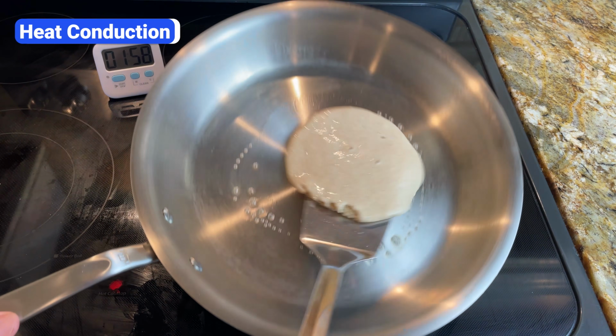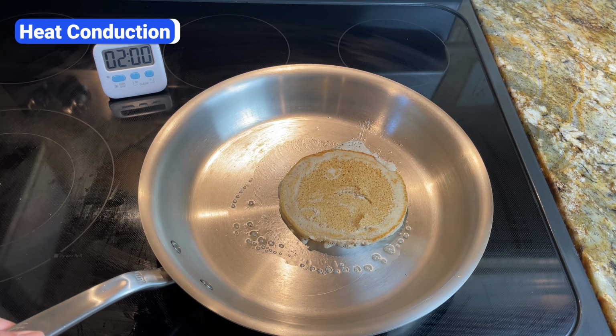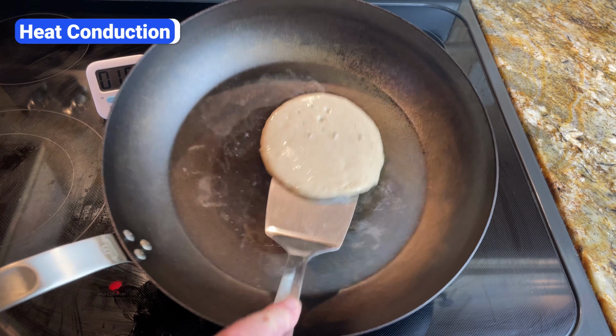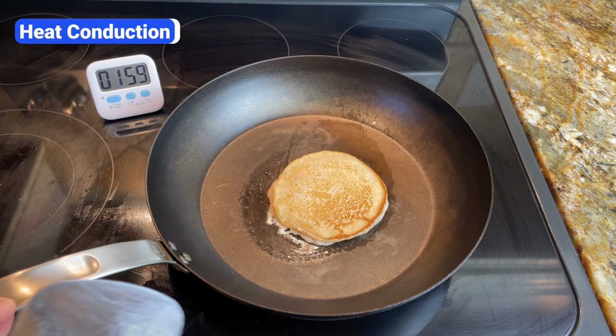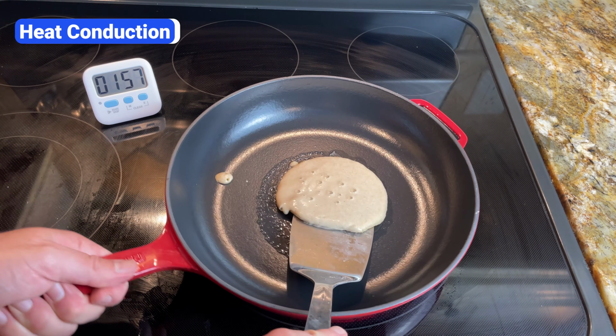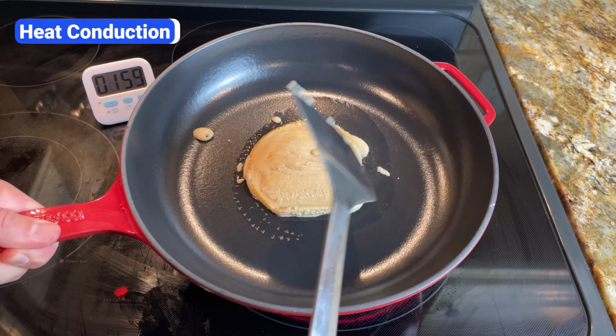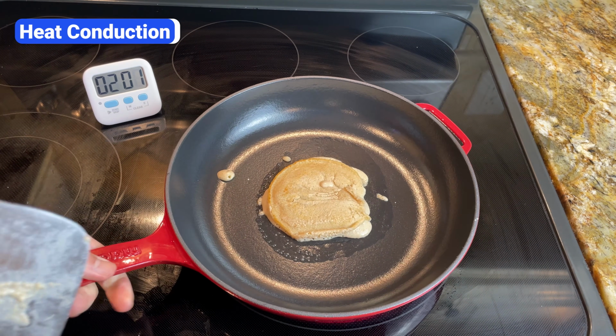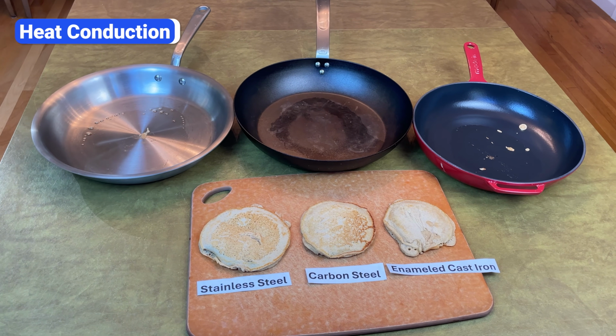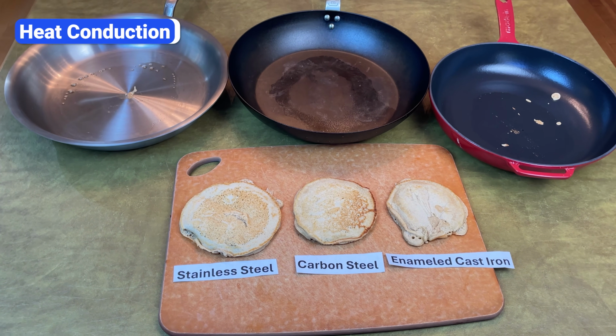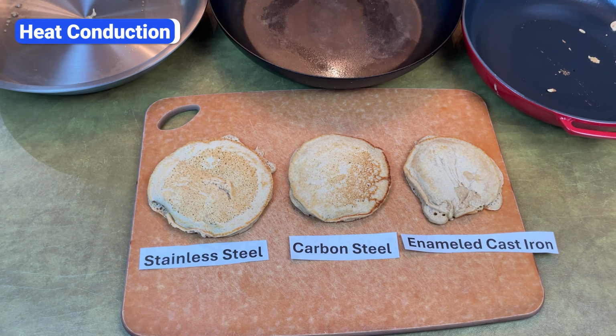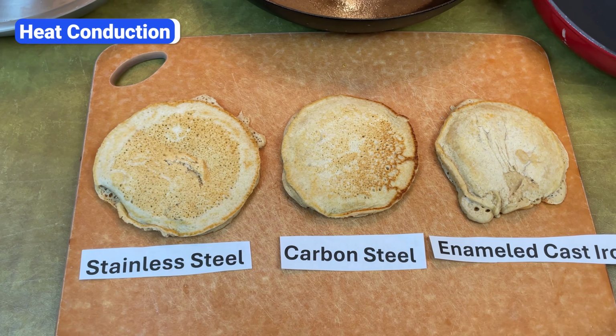The stainless steel pan cooked the pancake fast and evenly. Carbon steel heated quickly, but one side of the pancake cooked more than the other. And the cast iron pan heated so slowly that the pancake wasn't even close to done when the timer went off. The point is, carbon steel heats faster than cast iron because it's thinner, but slightly slower and less evenly than stainless steel because it has lower thermal conductivity.